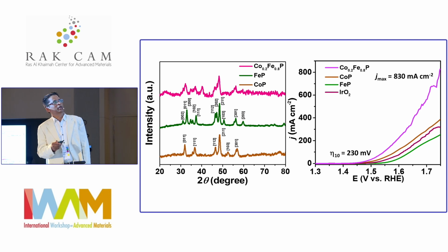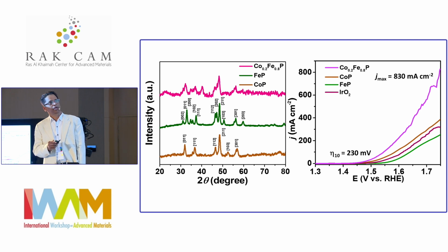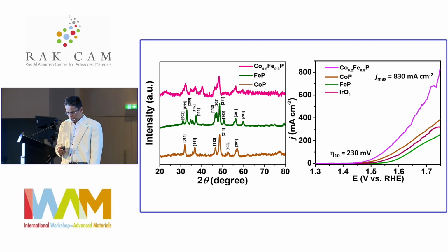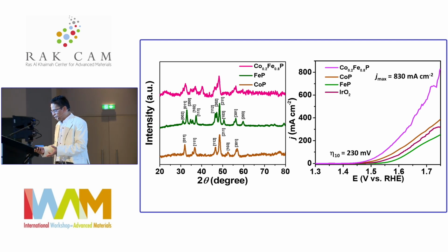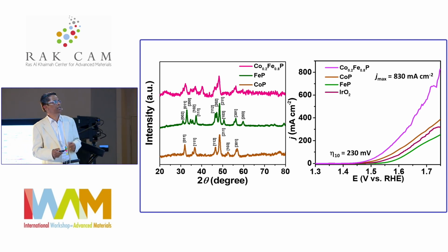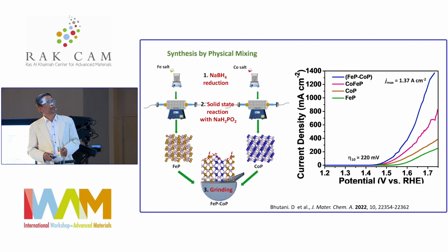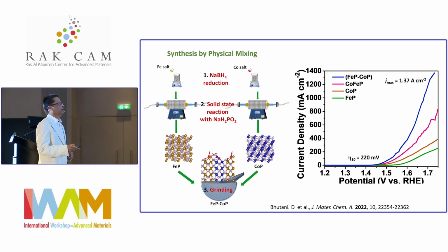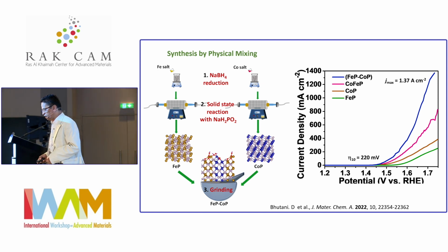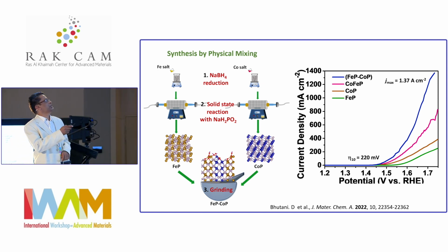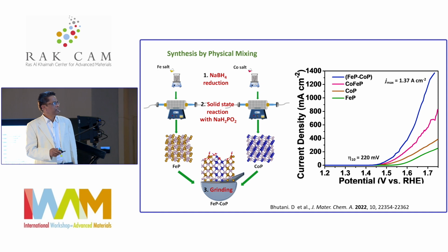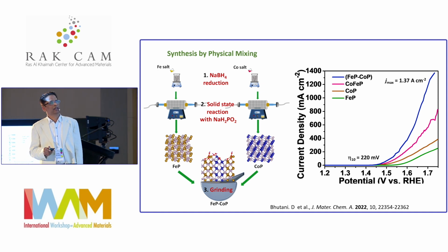Again, we optimized to get good activity at this ratio of cobalt 0.2 and iron 0.8 in this composition. Then we realized, if it is an individual phase, then if you make the two phosphides separately and mix and grind them, you should see whether you have the same activity. In fact, we made iron phosphide and cobalt phosphide separately, taking an iron precursor and cobalt salt, followed by phosphorization, then just mixed and ground them and looked at the activity by LSV.